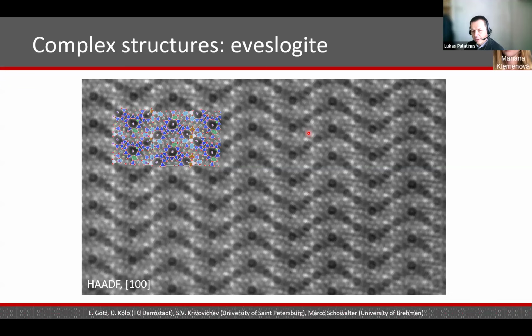The important aspect here is that it is a natural material that had literally thousands of years to grow. That was a slow process, and there was enough time for the material to really crystallize and stabilize in the thermodynamic minimum, so to say. So that is, I think, a very important aspect, the time that it took to produce this mineral. And also, I should emphasize one more thing: there are defects, but they are in the plane perpendicular to this view. So it's twinned. The material is frequently twinned, but the twinning does not affect this view. Nevertheless, the degree of organization of this mineral is really amazing.